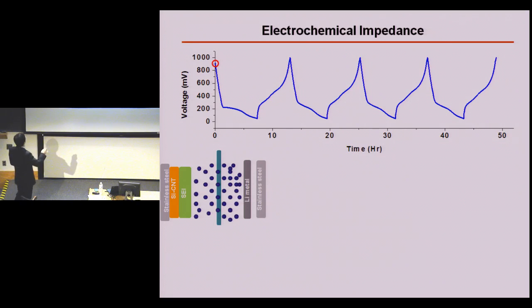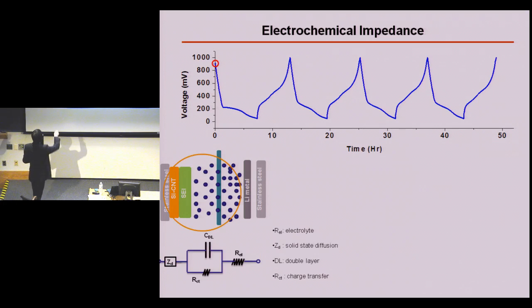So this is the device structure. You have silicon carbon nanotubes. You have the lithium metal. So you can see here, inside this current collector is basically an electron conductance. And in this layer, electrons will not transport, but the lithium ions will transport from lithium metal across the separator through this SEI layer, and then will diffuse into the silicon carbon nanotube structure.